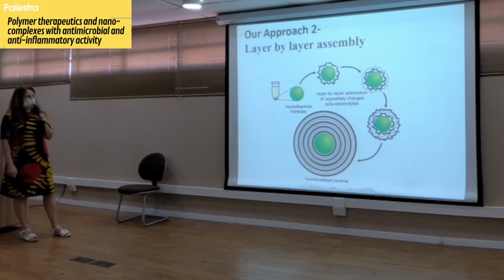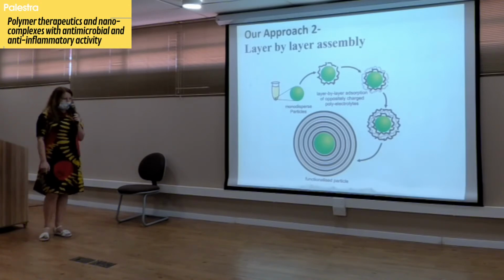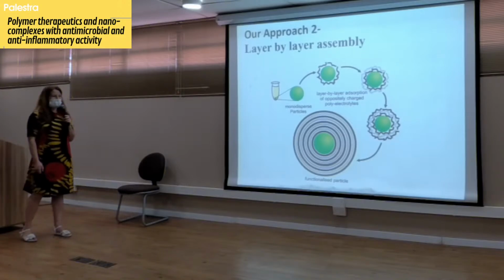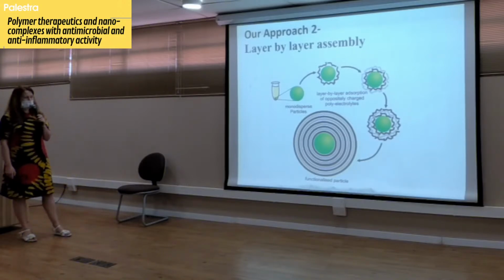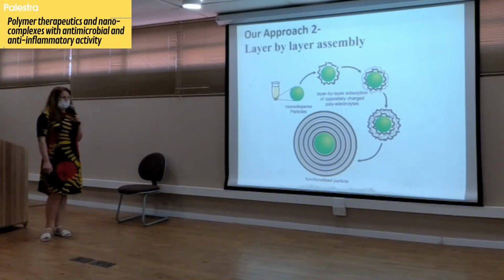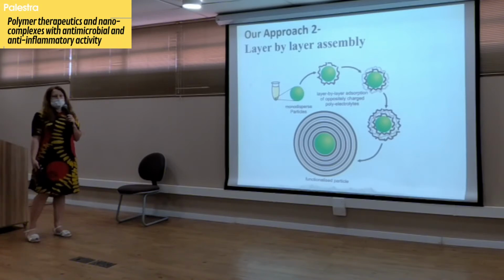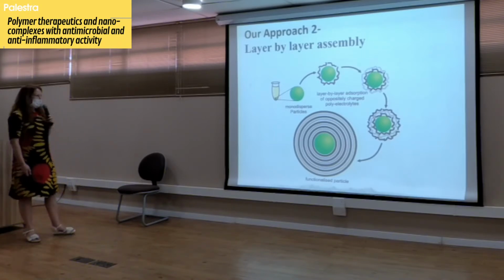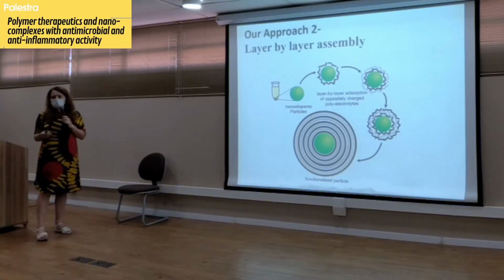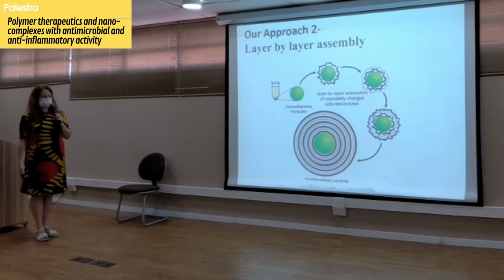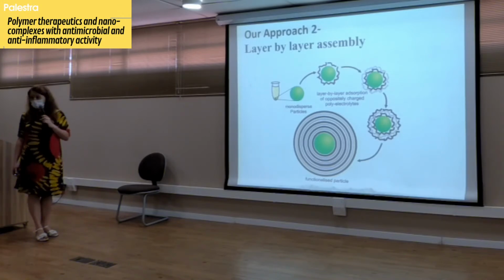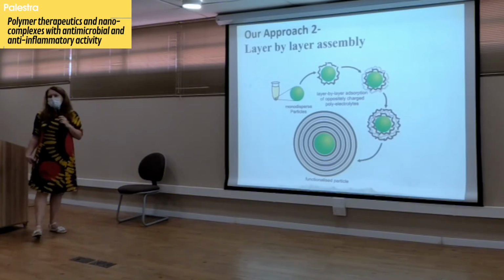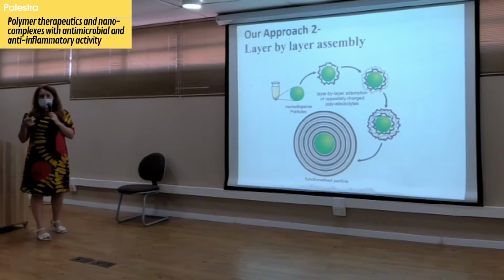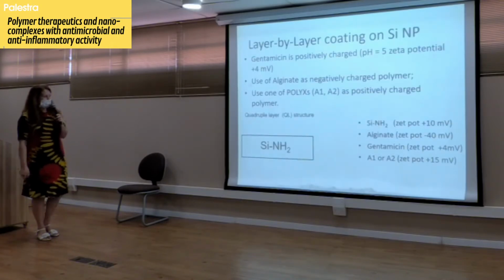We used a different technology. It's called layer-by-layer deposition or layer-by-layer assembly. So what is the principle of that? When you prepare your silica nanoparticles, you amino-functionalize them with amino groups, so you give a positive charge to your silica nanoparticles. After that, you start creating layers on top of that nanoparticle, based on electrostatic interaction. If your nanoparticle is positively charged, your first layer has to be negatively charged. The next layer will be positively charged, and so on. And we can entrap our small molecules, in this case gentamicin, between these layers. That's what we achieve.